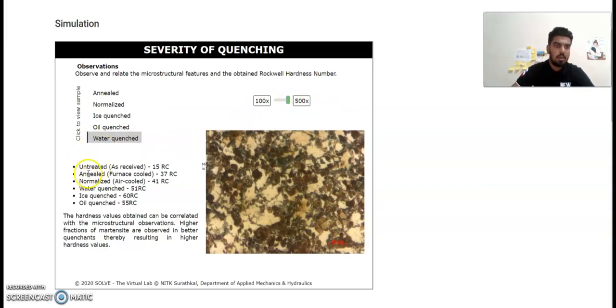Untreated as-received is 15 RC and annealed, furnace cooled, is 37 RC. Normalized, air cooled, is equal to 41 RC. Water quench is 51 RC. Ice quench is 60 RC. Oil quench is 55 RC.